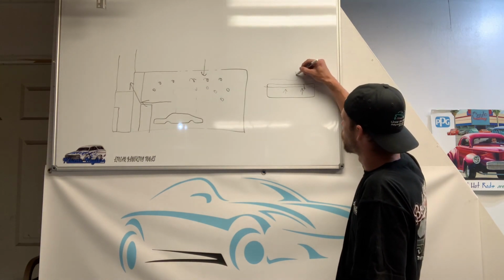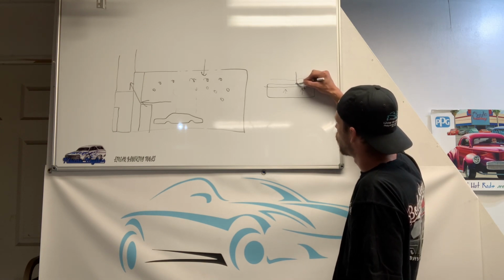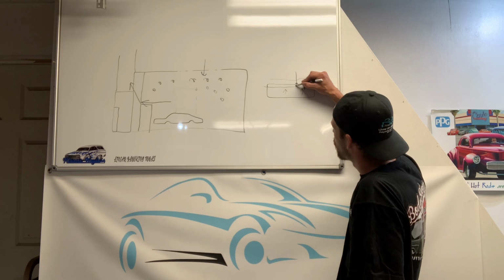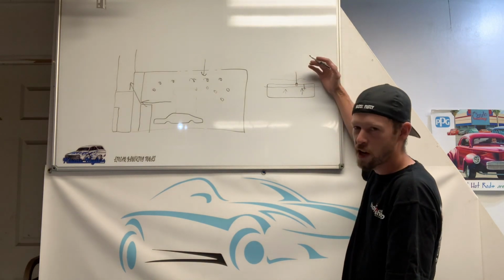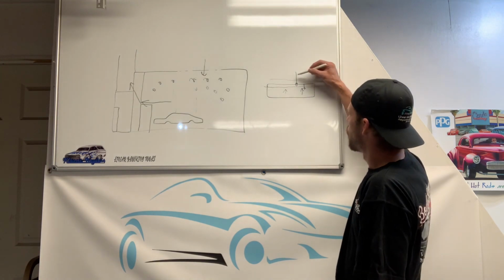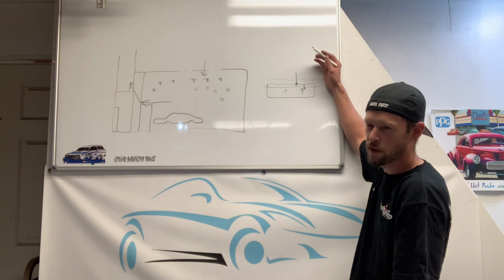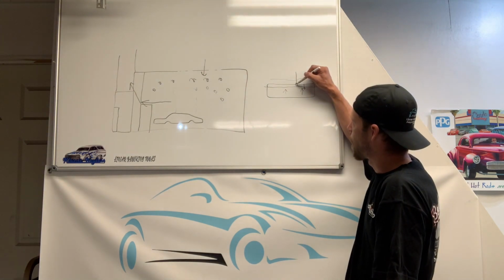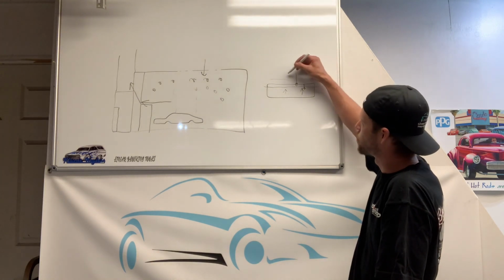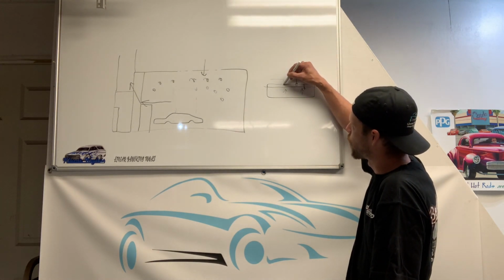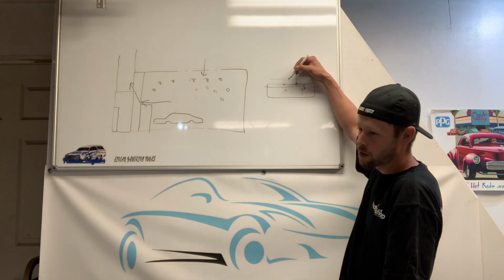Basically, the solvents that are coming down are recollecting, and it's softening that clear, causing it to kind of bite into that and create a crater or a little fisheye or a solvent pop. Now, when this happens, you probably won't see any fluid coming out of it because it's laid on the top, and over time it has dried out. But that solvent is coming down and re-softening that clear, and that tiny little weight of that solvent is creating a crater.